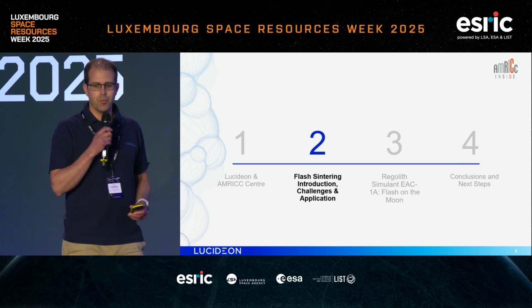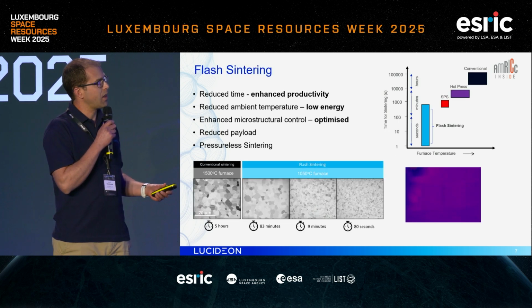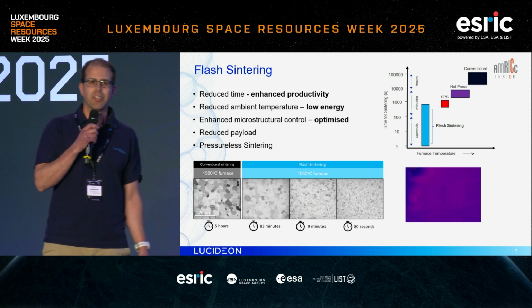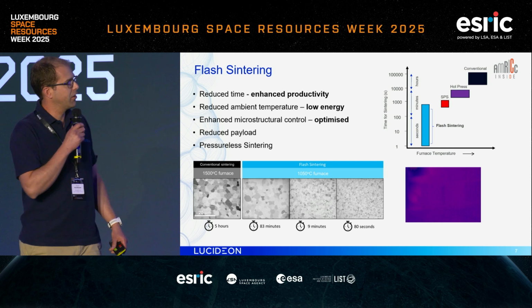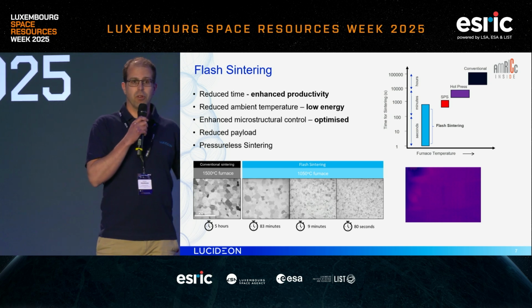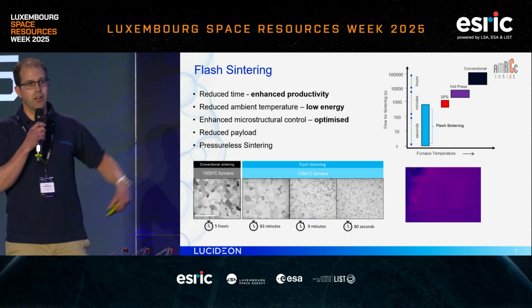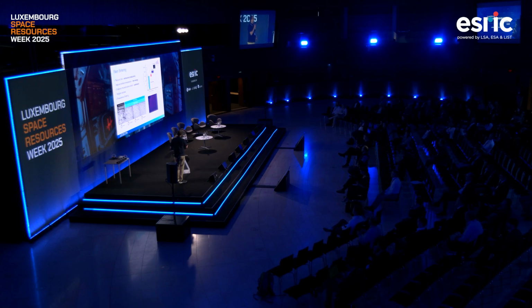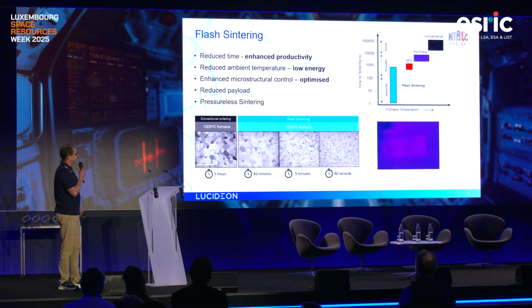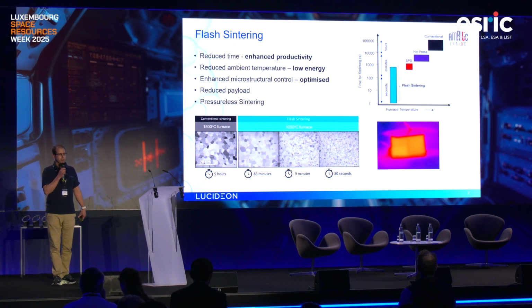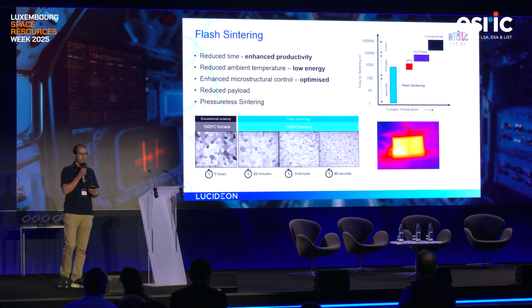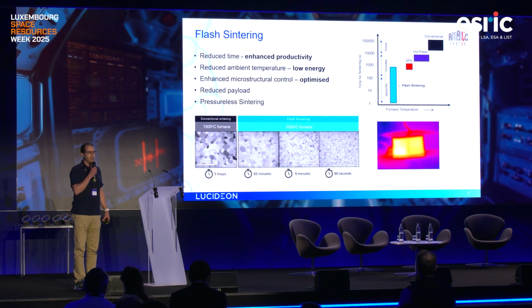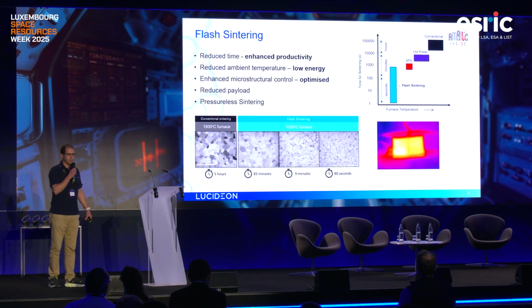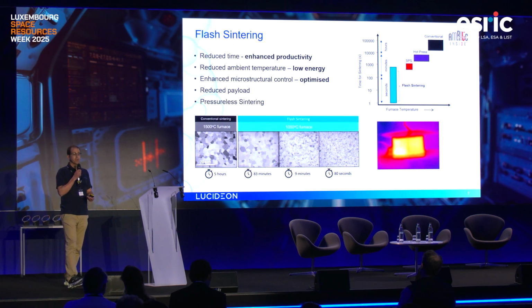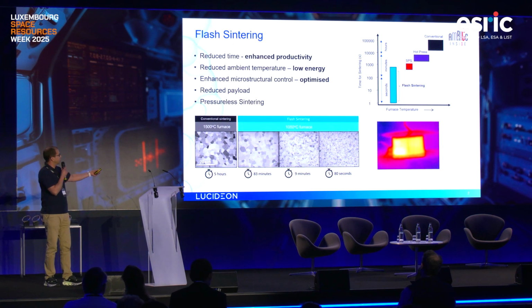So one of these key technology areas that I've been working in, and the technical team that performed this project, it is the application of an electric field to a ceramic during its sintering process. So we're heating the ceramic, the furnace, up to, let's say for the example that we're using here where we started, of yttria stabilized zirconia, a commonly used monolithic ceramic, we're heating up to 1050 degrees Celsius, and on the bottom right you'll see a video in real time. Sandwiched between two electrodes, we'll apply an electric field, and we see this rapid densification, this rapid sintering process occurring. So the interesting thing here is not only in terms of its ability to sinter ceramics at far lower furnace temperatures, but also the speed in which it does so. And then also the ability to control the microstructure.